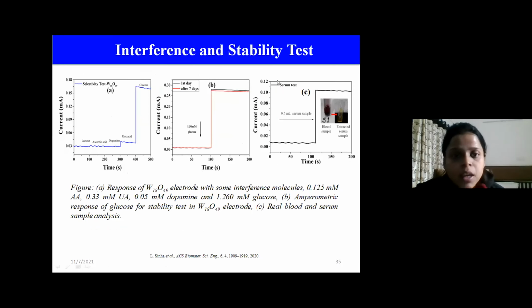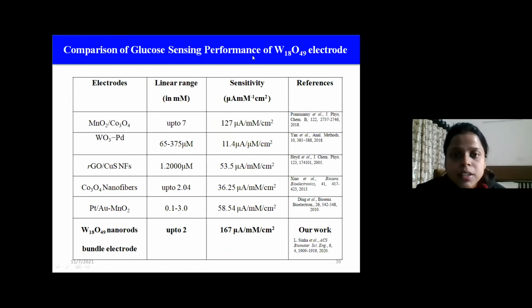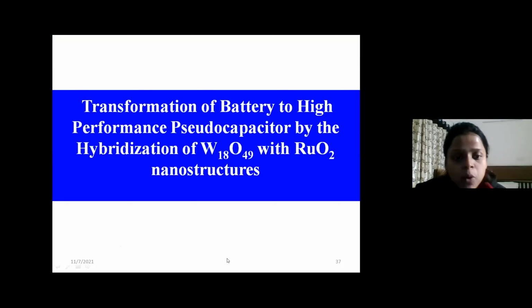0.02 micromolar. So interference and stability tests have been done, and even after 7 days the material is giving a stable performance, which shows the real use of this material for real blood and serum samples. This is the comparison of this material with other reported literature, and here we can see that this is giving a higher sensitivity.